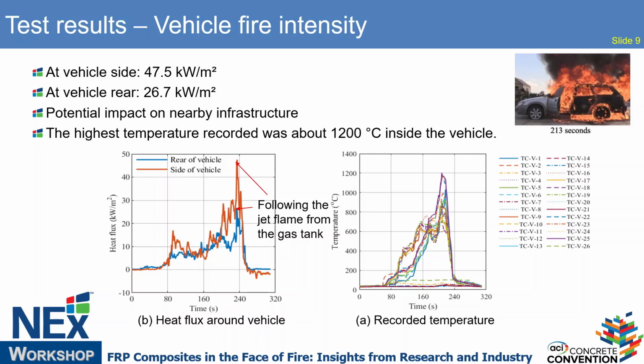And we didn't measure the external flame because it's an external fire, so the temperature will not reach 1,200 degrees Celsius. But what I found from the literature is that it should be something like 700 degrees, even for the external flame. So if this vehicle is below the bridge deck, such a high temperature will lead to some issues for the steel bridge or composite bridge deck.